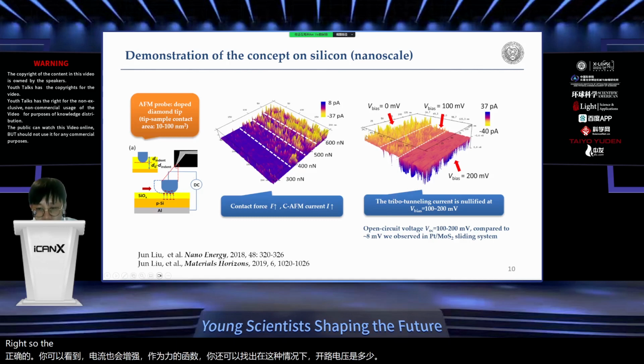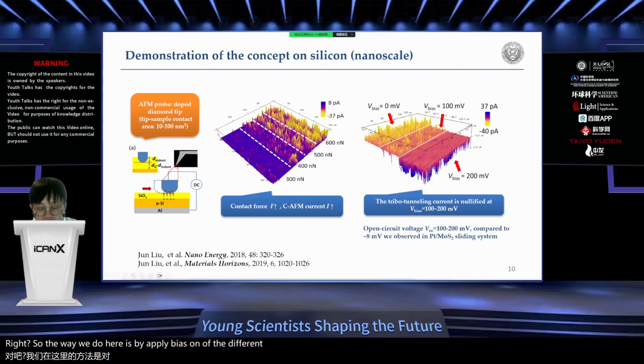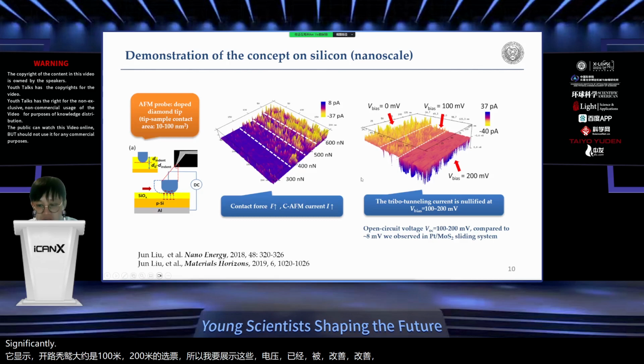And also you can find out what is the open circuit voltage in this case, right? So the way we do here is by applying a bias of the opposite polarity and seeing at which bias the current will decrease to zero and reverse, right? And then in this case, it shows that the open circuit voltage is about 100 to 200 millivolts. So I'm going to show that this voltage has been improved significantly in recent years.